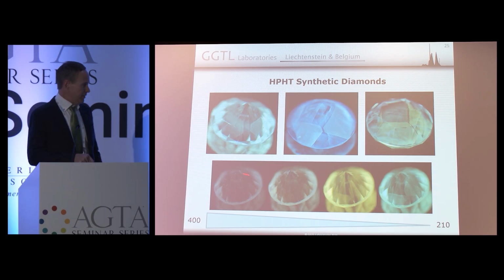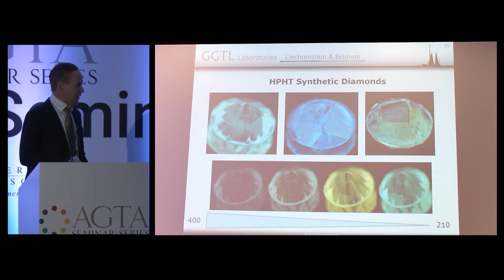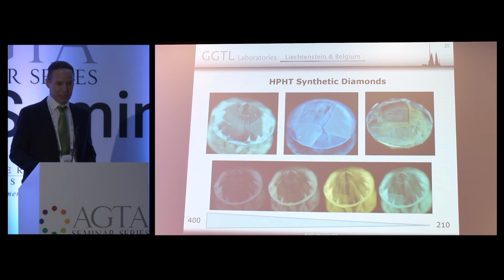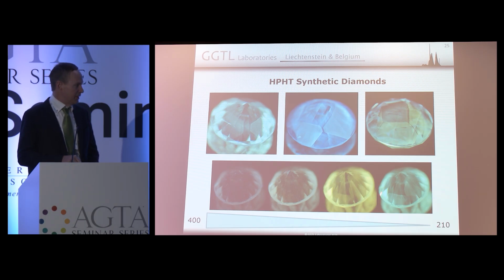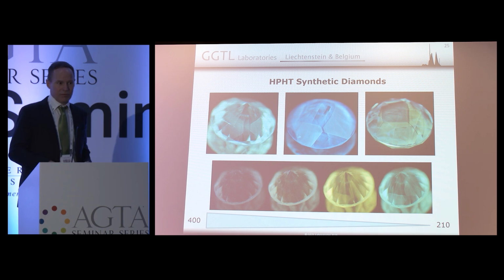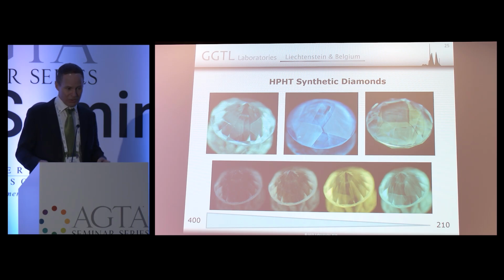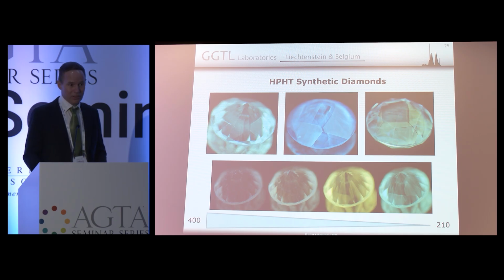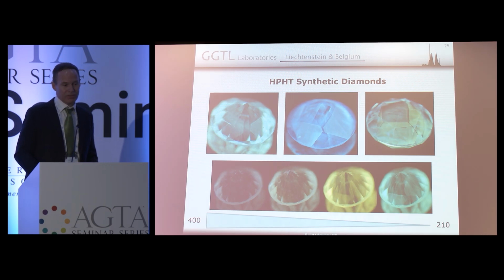So here we are at long wave. Most HPHT synthetics at long wave UV don't do anything. They're usually inert, generally speaking. And the shorter you go, the more they fluoresce. So at 254, you do see it, and you do see also a sector in here, but it's generally much less distinct than when you go to deep UV, where you see this. What these things also do, they phosphoresce long-lasting. That's nothing new. It has been published on many occasions. Most don't know why, but it's actually because of boron. So these stones almost always contain a mini trace of boron. This is the reason why they phosphoresce long-lasting.